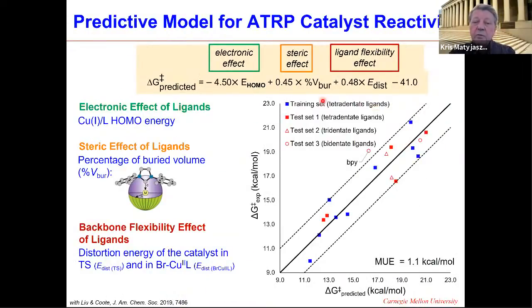If you move now to the catalyst, there are really three parameters which are very important. One is the electronic effect, which can be defined by the energy of the HOMO level. And the other one is the steric effect. The alkyl halide must come inside the cavity of the ligand, so it can be defined by the percent of buried volume.